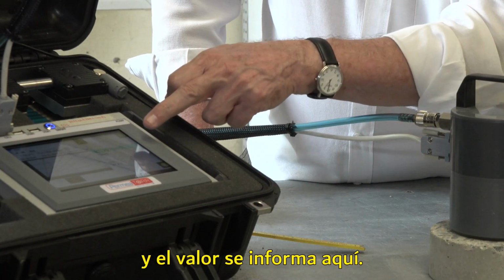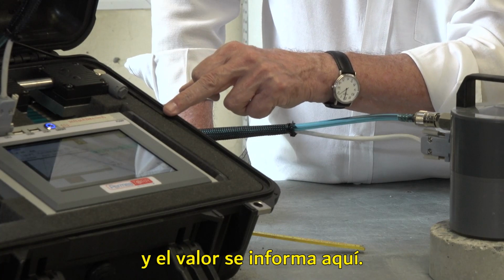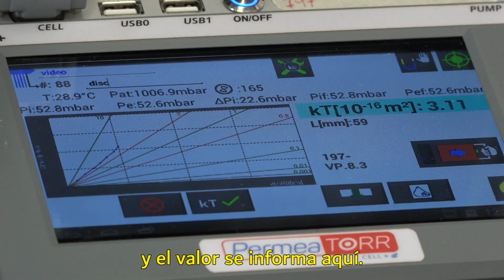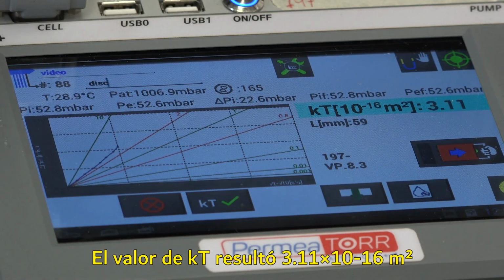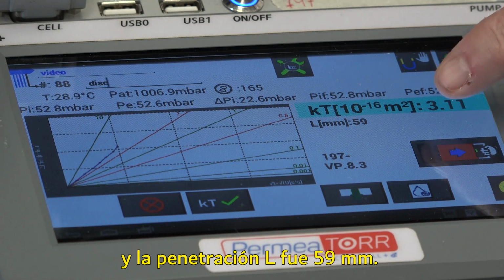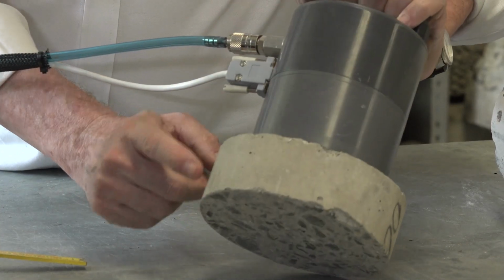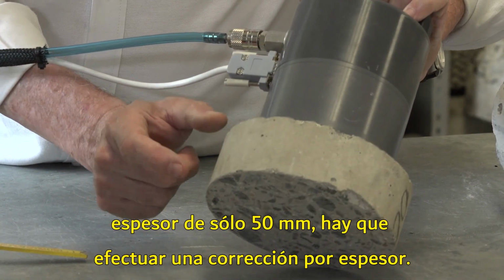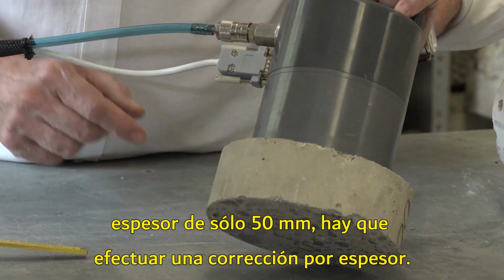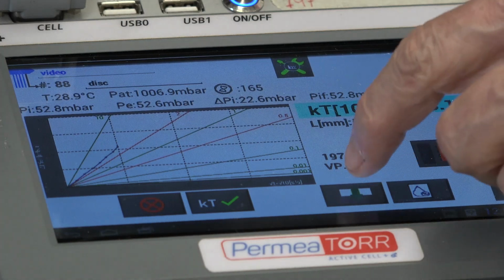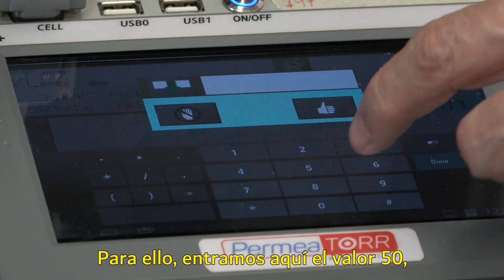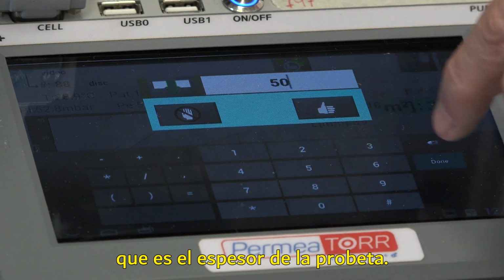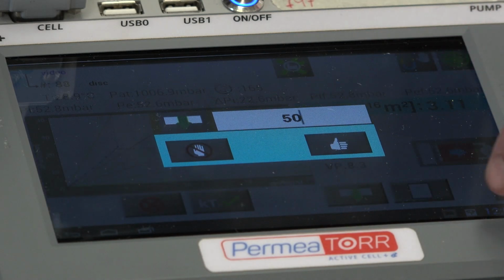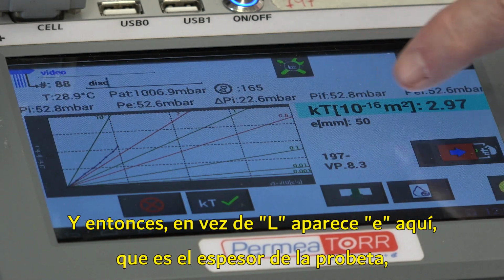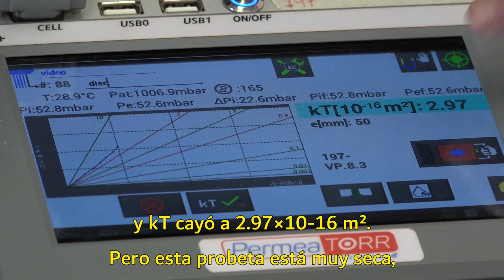And the value is reported here. So the value is 3.11, and the penetration of the test is 59 millimeters. Now, as the sample has only 50 millimeters, we have to make a correction for thickness. And therefore, here we enter the value of 50, which is the thickness of the element. And then instead of L, we have E here, which is the thickness of the element.